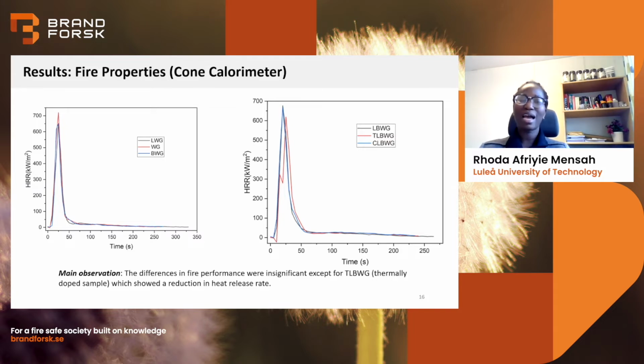But if we look at the doped samples, we see that the TLBWG, that's a thermally doped sample, had the lowest peak heat release rate. That means it has the highest fire performance. The next one.